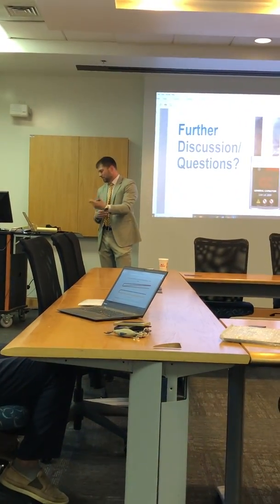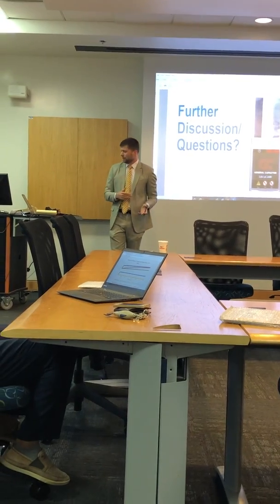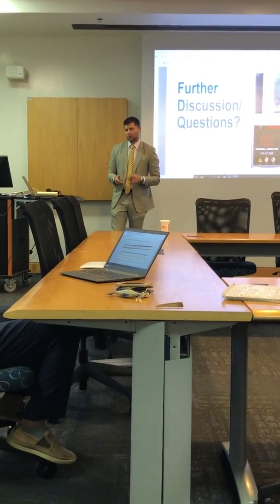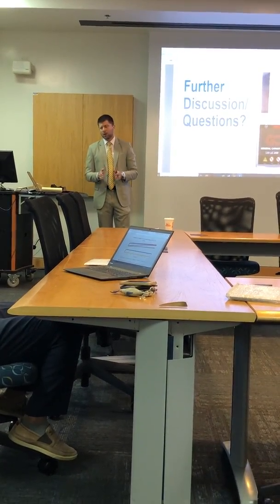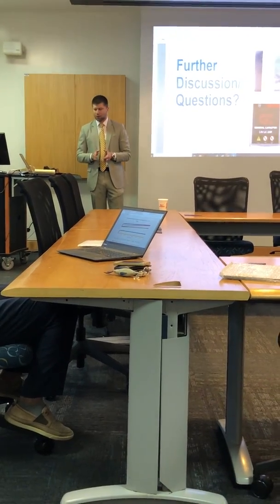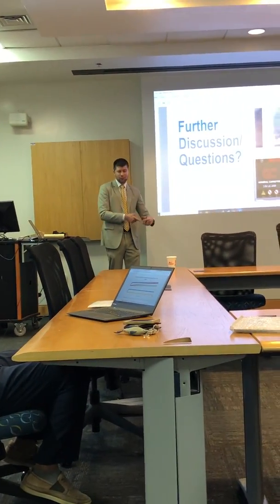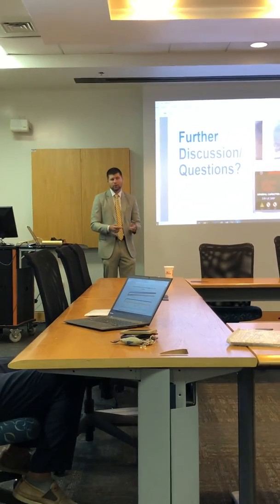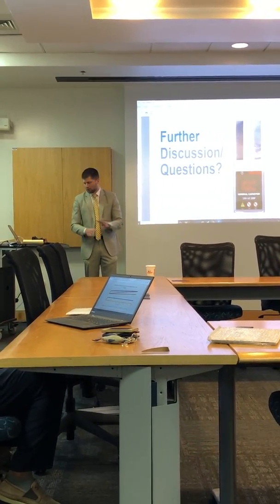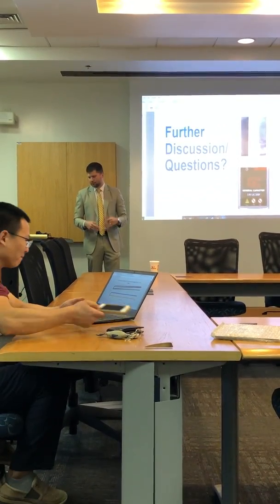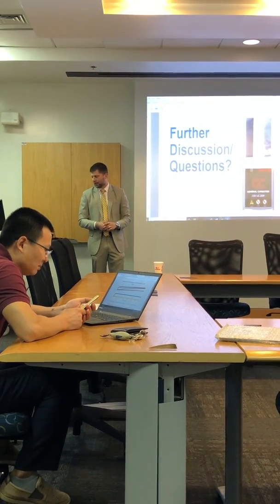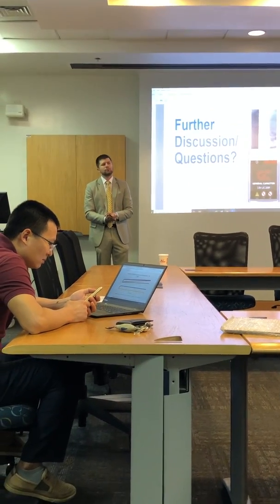If that value starts out at 0 before anything's begun to intercalate, that'll confuse the model on the exchange current. So the way I accounted for those is, in both situations, I told the model to start out at a value that was orders of magnitude smaller than what the actual value would be, just so that it could avoid having an undefined error and be able to continue.